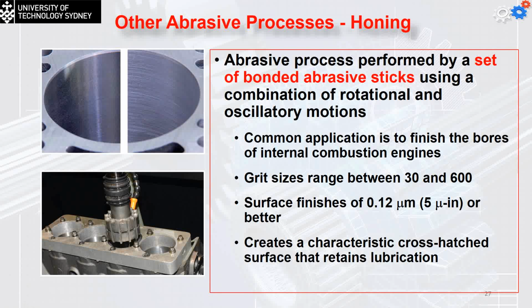Common application is to finish the bores in internal combustion engines. The grit size for the stacks is going to be between 30 and 600. The surface finishing is going to be about 0.1 micrometers or better. And it creates a characteristic cross-hatch surface that retains the lubrication. So we do that on purpose. Usually we can do it as a mirror shape, but we need to get some cross-hatch surfaces to retain the lubricant during the operation of the engine block. So this is the honing process.